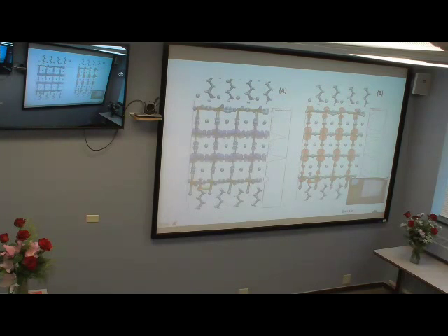This is a three-dimensional structure, represented periodically, though the thin film has two-dimensional features. Here the surface is completely isolated by this ligand, so the ligands do not contribute to the HOMO-LUMO gap, while the other one has these orbitals at top and bottom completely occupied, and this probably caused this difference in the band gap. So the organic layer works as an insulator, and the inorganic does not.